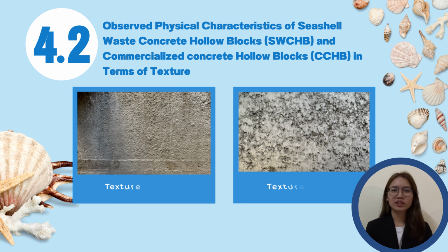The first figure shows a smooth texture of the seashell waste concrete hollow blocks produced using a design mix, indicating a meticulous formation process and a proficient smoothing process. Contrasting the first figure, the other figure depicts the texture exhibited by a concrete hollow block manufactured by a specific company. The visual representation highlights a distinct disparity, revealing a rough texture characterized by the presence of noticeable air pockets and numerous surface fissures. These discernible physical properties observed in CCHB strongly suggest that it was not formed optimally and may have been subjected to external factors, leading to fissures and accumulating air pockets.